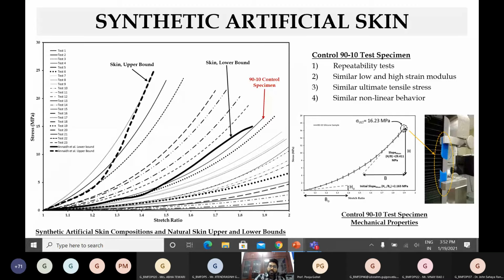The second thing which we do is we create a control specimen. Control specimen meaning one single specimen, and we run a battery of tests on that specimen to look at repeatability, several other properties, linear and nonlinear properties, ultimate tensile stress, which is the fracture property, and the overall nonlinear behavior across a lot of different strain rates and whatnot. Okay, so that's step two. The first step is we narrow down from a hit and trial kind of basis certain composition ranges. The second step is we take one of those key compositions and we keep on running repeatability tests.